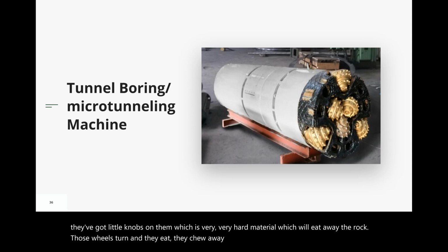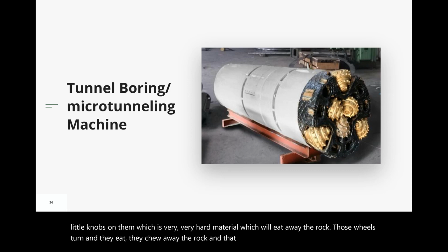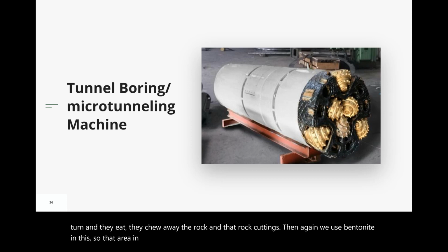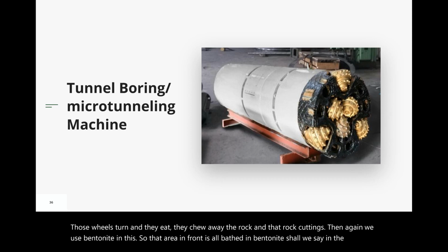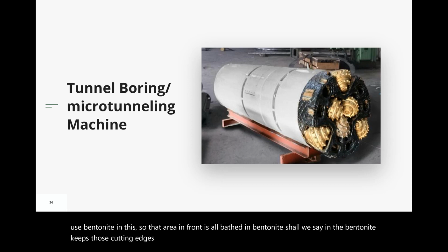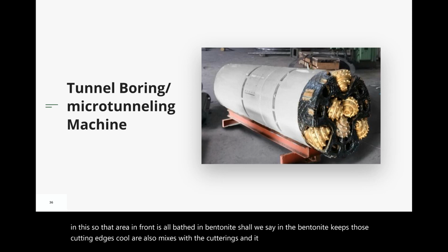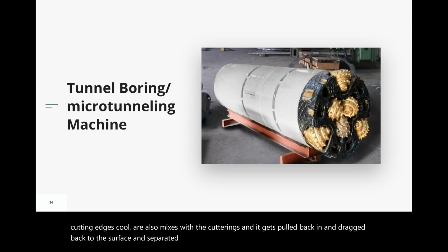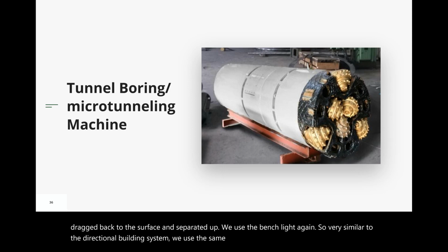And then if you look at the breaks in that machine, in the white colored pipe section of the machine, those breaks, they're actually hinges. And so there's jacks inside there that cause that hinge to move, which allows me to steer essentially. So I can steer vertically and horizontally, and I would have lined up this machine from the very back with lasers, and I can steer this machine.